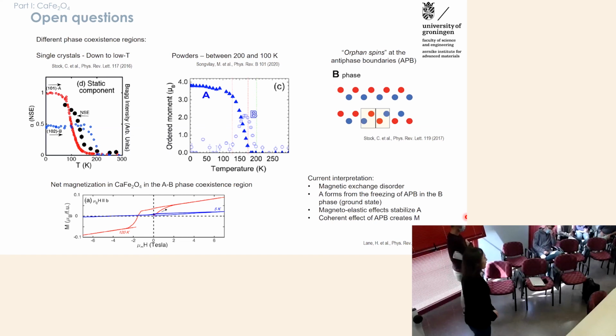So we think that there is not this extra iron, because especially Mossbauer is really sensitive to all the iron species. So we don't see any metallic iron atoms in our signal. We only see the two iron positions that belong to the iron in calcium ferrite. So what we think is actually that the problem here is during growth. There is not a perfect stoichiometric transfer of the stoichiometry of the targets to the films, and we are losing, especially at the beginning of the growth, some iron.